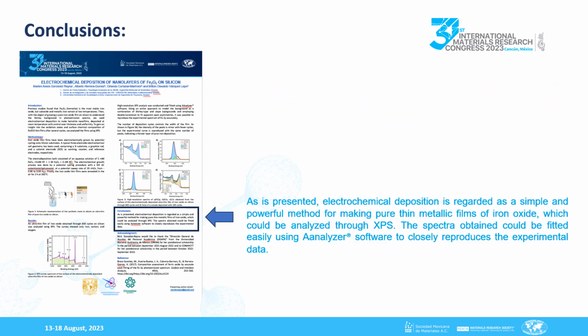Electrochemical deposition is regarded as a simple and powerful method for making pure thin metallic films. The XPS spectra could be fitted using Aanalyzer software, reproducing the experimental data with double Lorentzian forms and Shirley, Sloping, and slope backgrounds.